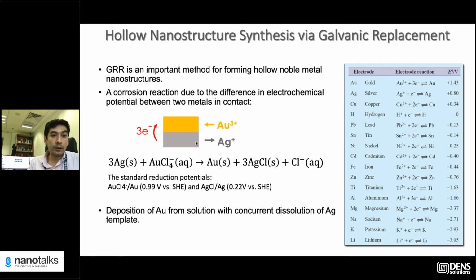You have a silver underlying core metal, and then let's say you have gold ions in your solution, which is 3+. When it deposits, it creates 3 silver ions, which then dissolve in the solution, right? So this is how you essentially hollow the silver out. And as gold continuously deposits on the surface, you end up with a shell kind of structure, but the interior of the material gets etched away.